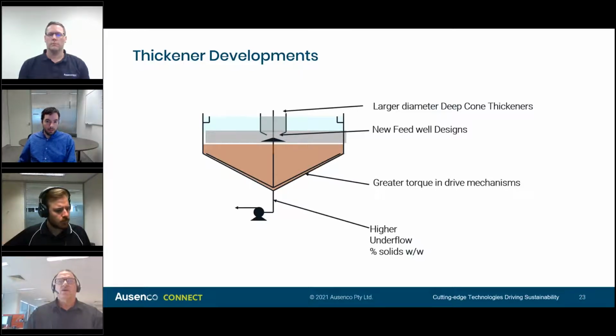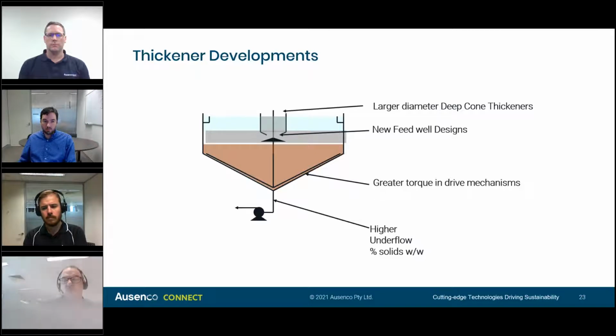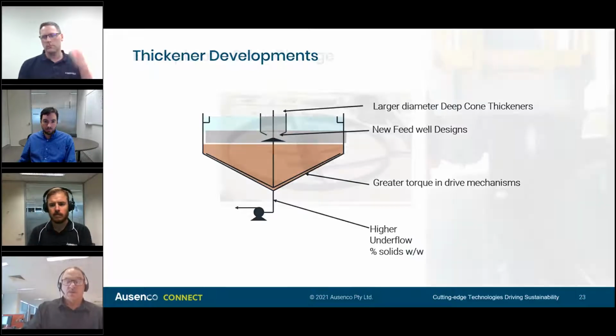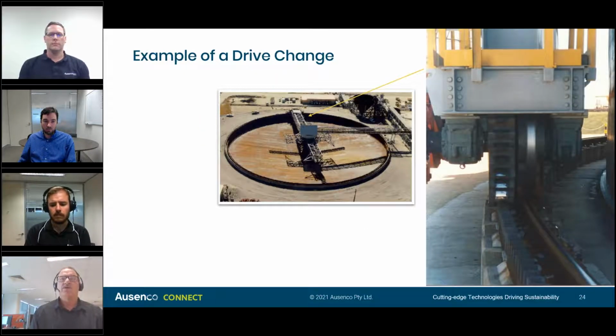We've gone to basically larger drive mechanisms, which can accommodate much higher torque. And we've also been able to understand rheology a lot better and move to pumping thick viscous material much further out than previously. So improved flocculant thickness have grown taller as opposed to smaller. So in this example here is a periphery drive of a large thickener, and the drive is actually on the circumference of the thickener, and you could get up to 16 million Newton meter torque on this particular thickener.